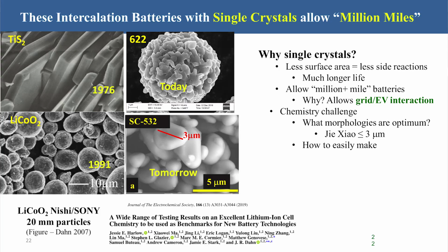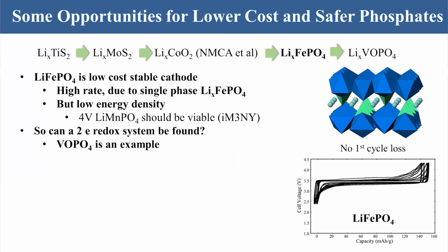The next challenge really, what are the best single crystals? What shape should we use? Now, do we want octagons, plates? And this again, my colleague Jie Xiao is working on this. And she says if you keep the single crystals below 3 microns, they will not crack. And we learned that with TiS2 as well, keep them below a certain size. So now we have to find out how can you easily make single crystals in an economically viable way. And I should emphasize these NMCs, they're not economically sound manufacturing. The firing is all batch processes in pots, is not a continuous process. And that really needs to change.